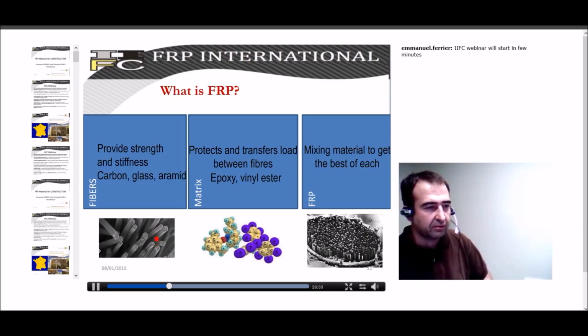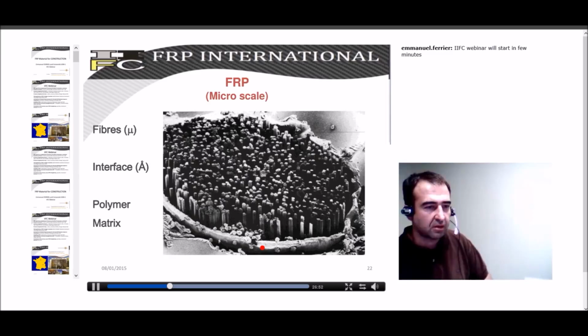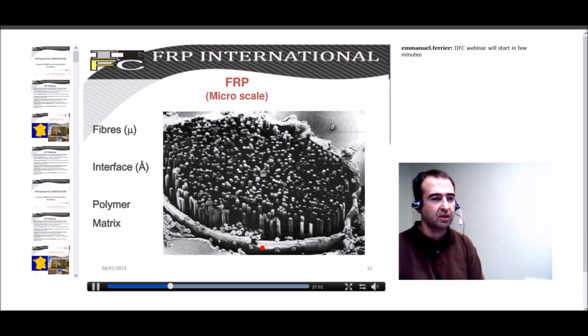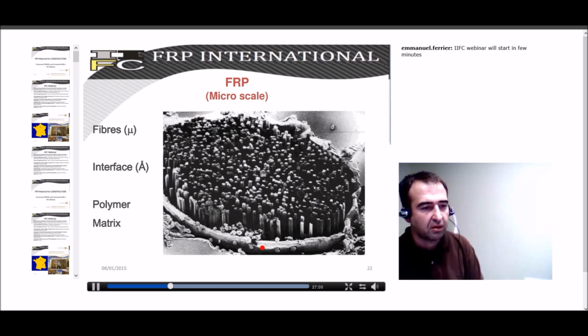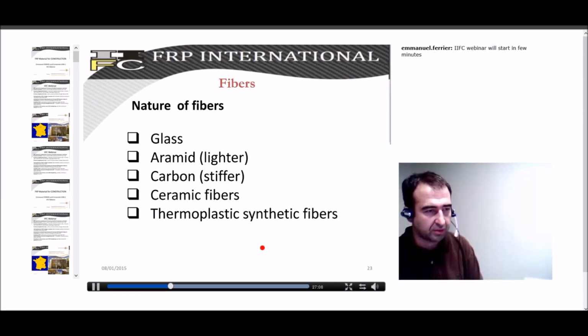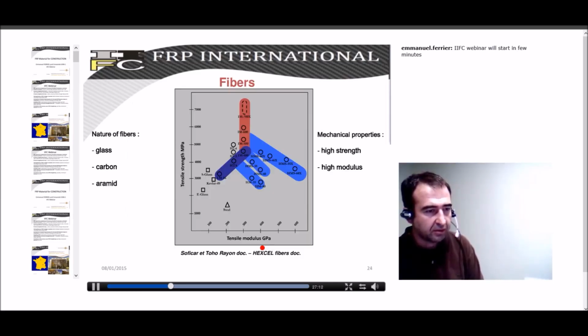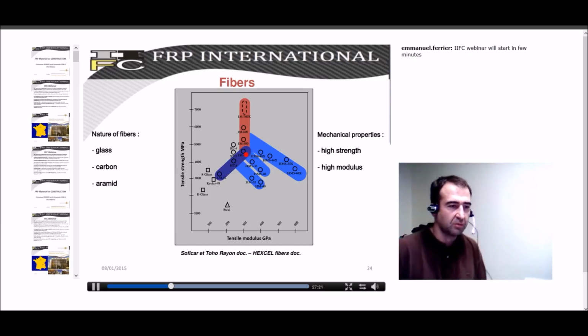FRP material is made of fibers, mainly carbon, because people started with these fibers, but also glass and a few examples with aramid fibers. The matrix is essentially epoxy, and the material you get has a lot of small fibers that play the same role as steel rebars, but with lighter properties. About the fibers, you may know that carbon fibers, high modulus or high strength, are commonly used.